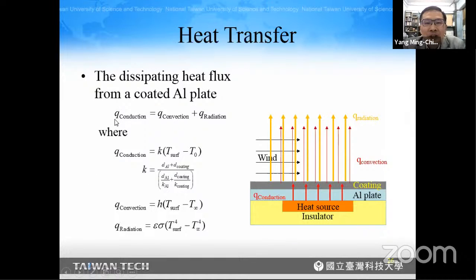These are the equations. I think these are very familiar to the students because they are taken from the textbook. Basically, the conduction heat flux is equal to the convection heat flux and also the radiation heat flux, and their equations are given below. In the case of conduction heat flux, it is the conductivity times the temperature difference from the bottom to the surface. Because it is a composite containing both the aluminum plate and the coating, the conductivity is calculated from this equation.